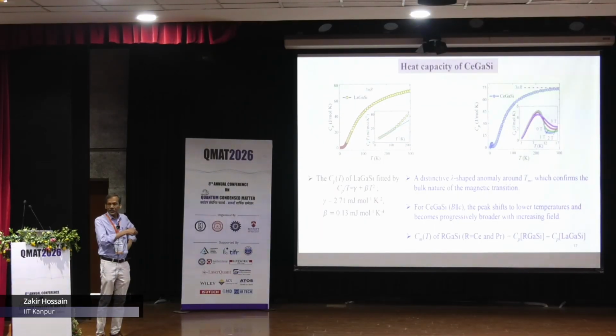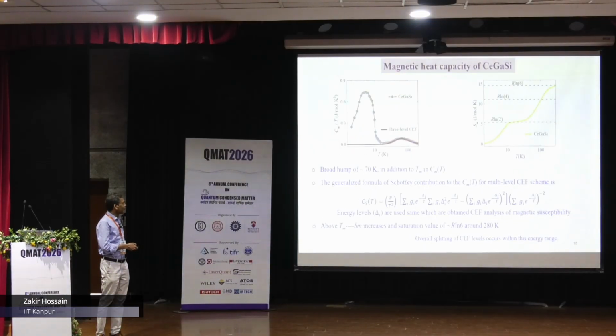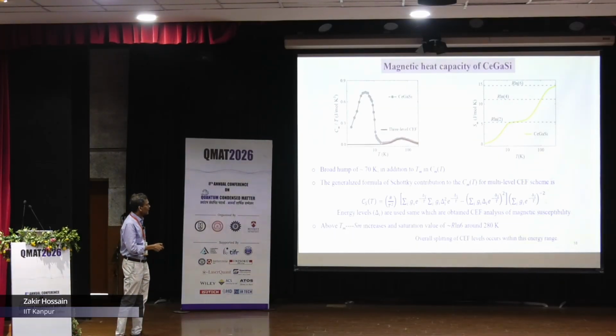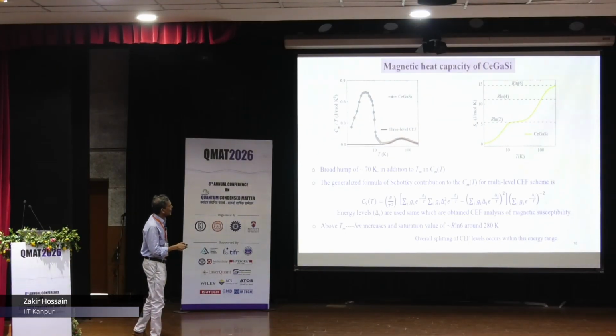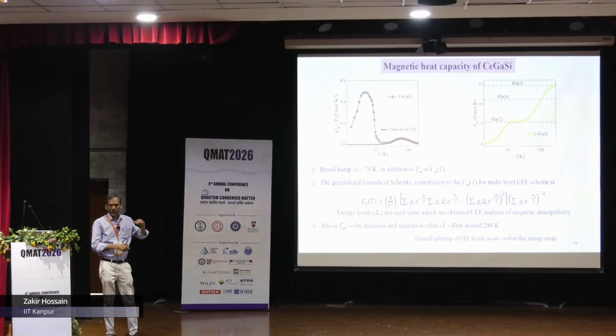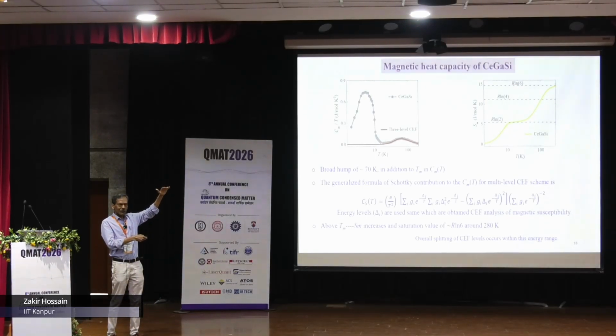We also, from heat capacity, using this C/T versus T, then take the entropy. So you can check the entropy, and the entropy also is consistent with the proposed crystal field scheme, because you see that there is one R ln 2 which is happening at about 10 Kelvin. Our first level was far above that, and then R ln 4 we are getting here at about 100, and then R ln 6 we are getting within 300. All 6 levels were below, the highest was about 288 Kelvin, which is consistent.